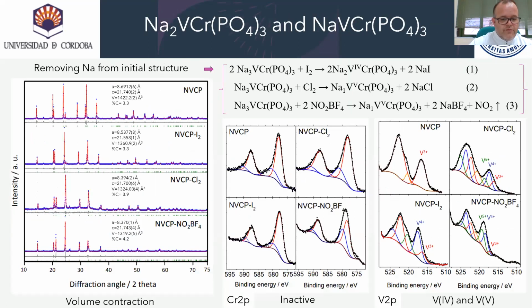In order to remove the contribution of mobile sodium in the initial structure, chemical desodiation of NVCP was tested according to the three reactions. For chemical desodiation, we use different oxidants: iodine, chlorine, and NO2-BF4.